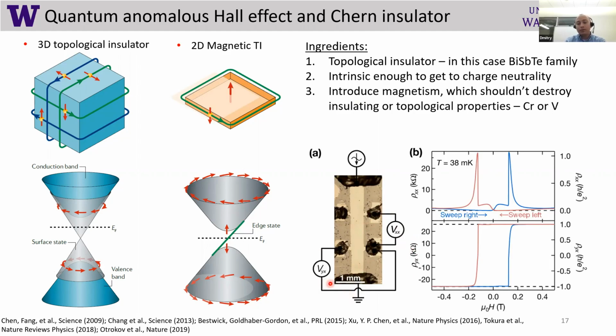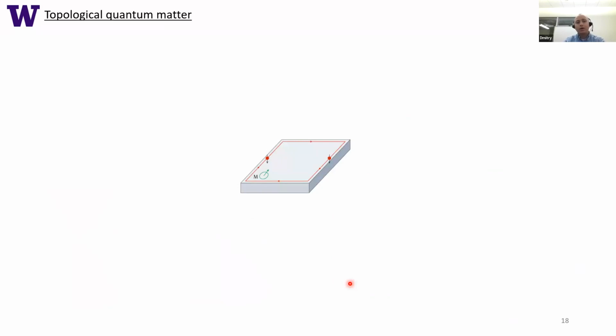And now people can build essentially millimeter-sized samples of quantum anomalous Hall insulators. And the resistance there quantizes very nicely at very low temperature. So you can see this beautiful loop. You can also notice that in contrast to the quantum Hall state, you don't actually need any magnetic field. Because of the magnetism, you already have Chern number control. So you don't need any magnetic field to create these chiral edge modes. And the size of these samples for mesoscale physics is actually enormous. It's very large.